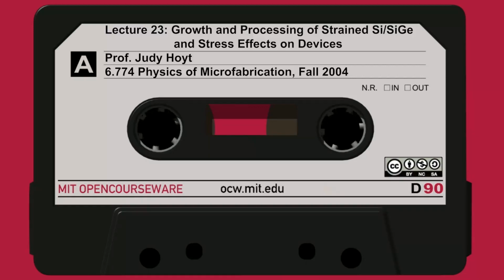So the idea was, what if you could take this layer, since the top portion looks pretty good, bond it to another wafer, and then etch away all of the dislocated material? You'd have relaxed silicon germanium on insulator, and all this dislocated material would have been etched off, or maybe removed by a smart cut-like process. I think some of you are studying smart cut; we talked about it when we talked about SOI formation.